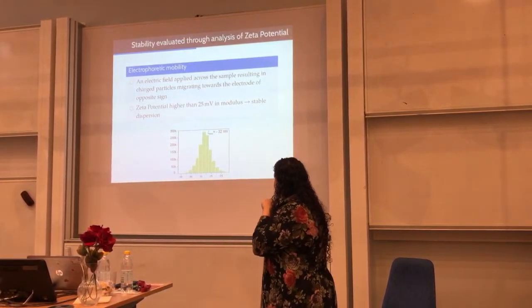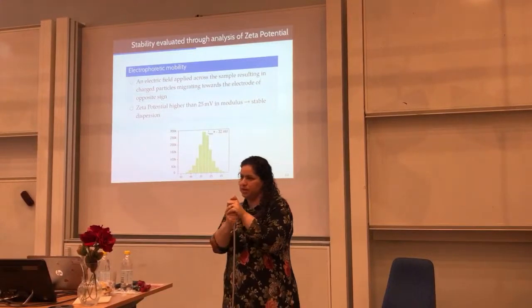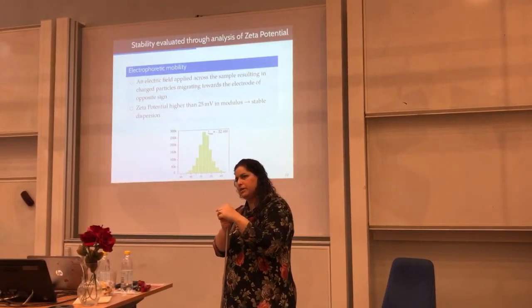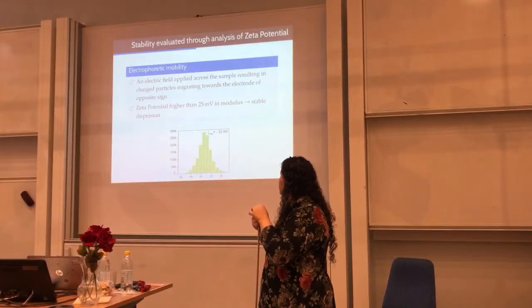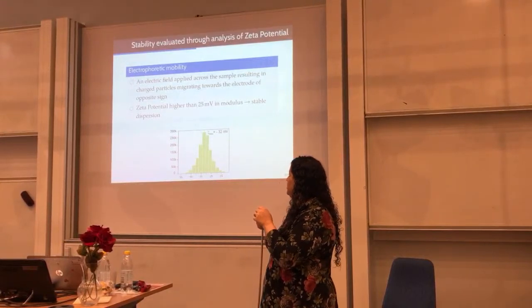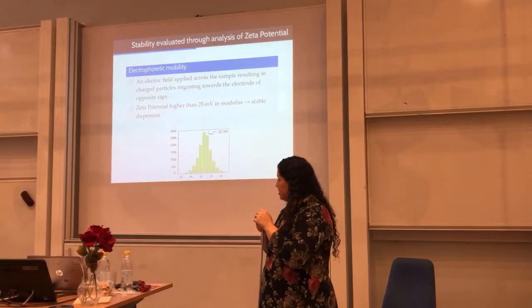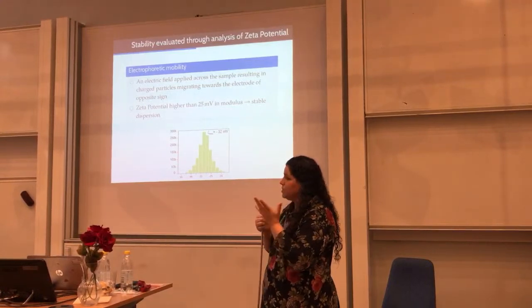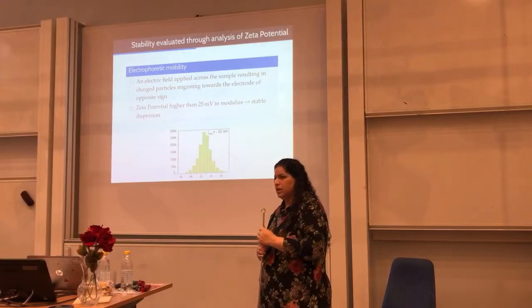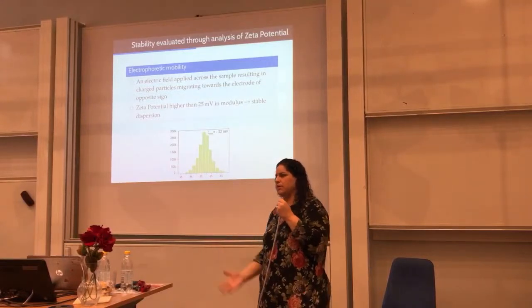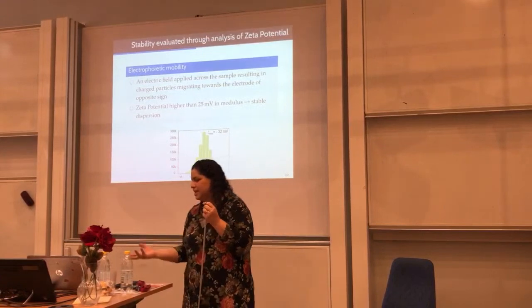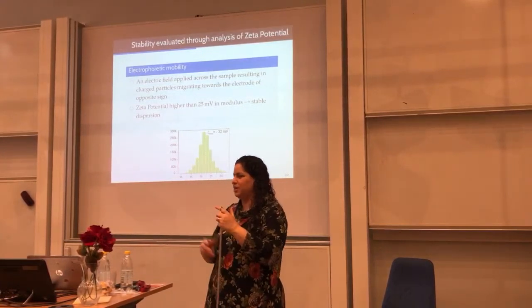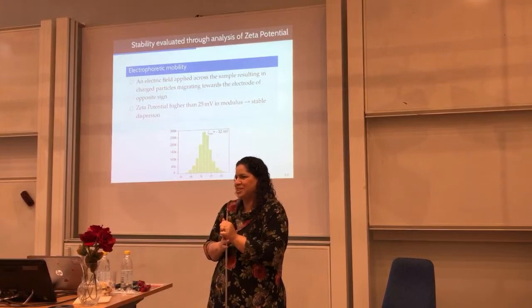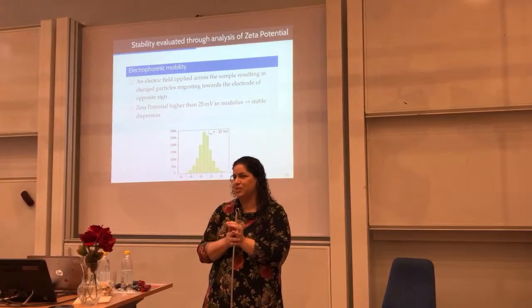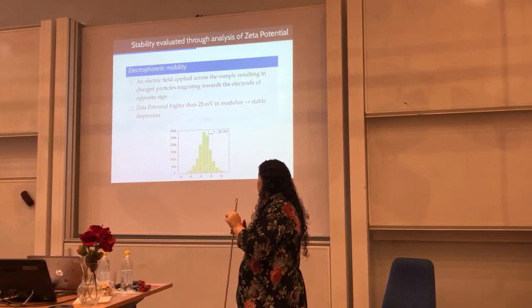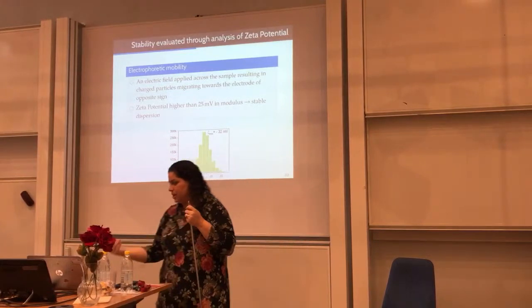So we talked about the size of the particles, we talked about the thickness of the particle, and the last open question about this liquid phase exfoliation dispersion that we always have to take care of is the stability. How long is the shelf life of these materials? Because it doesn't make sense, if you exfoliate and then you have them on the table and they sediment, then basically what you did is worthless. So the shelf life of these particles has to be strong enough that you can commercialize.